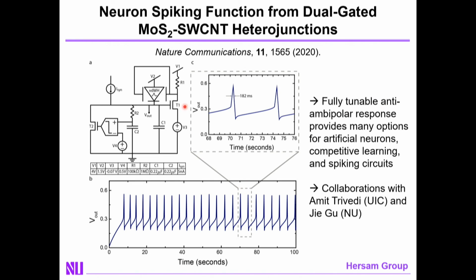And that's indicated here. I take one of those mixed dimensional van der Waals heterojunctions. I combine it with some simple circuit elements like resistors and capacitors. And if I input a synaptic current into the circuit, the resulting voltage as a function of time is a spiking response, where the details of that spiking response faithfully mimics that of an action potential in a biological neuron. What's interesting, though, about this artificial neuron compared to a traditional biological neuron is that we can tune the details of the spiking response just by changing the voltages applied to the device. So it's a highly reconfigurable artificial neuron.